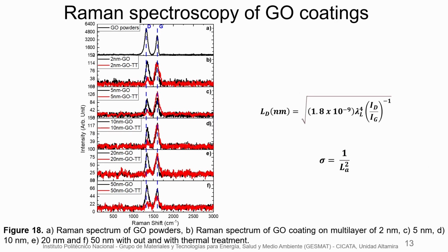Raman spectroscopy of the graphene oxide coatings are presented. We have in the upper part the Raman spectra of the graphene oxide powders used for obtaining the graphene oxide coatings. Then in A, B, C, D, E, and F, we can see the Raman spectra in black of the deposited graphene oxide coatings, and in red the Raman spectra of the graphene oxide coatings after thermal treatment. We can observe the well-known D and G bands for graphenic materials.